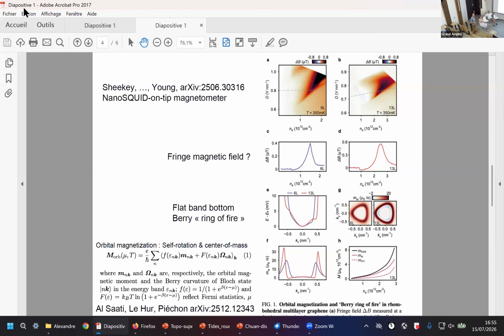If you would draw the Dirac cone of a monolayer of graphene, you would see that it has a very large velocity compared to that. First, it looks parabolic, but also it's very flattish compared to the Dirac cone. And also what they see here is a plot of a quantity related to Berry curvature, called orbital magnetic moment coming from self-rotation. And they see a region around the K valley, a ring where this orbital magnetic moment is very large.